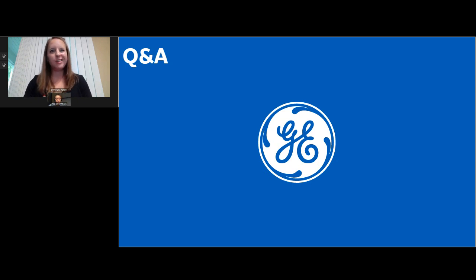So if there's a particular critical feature that has a very specific and very stringent fatigue requirement, you may still want to go back and machine that. However, with additive manufacturing, the design freedom that you have also allows you to redesign your component if possible and can change your stress distribution to change what those critical fatigue loaded features actually end up being. So I'll say, yes, there are fatigue loaded components that are being used in the as-printed state.